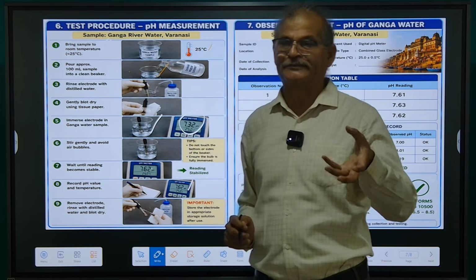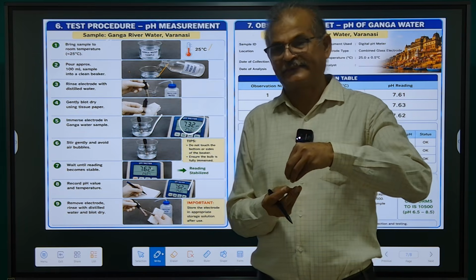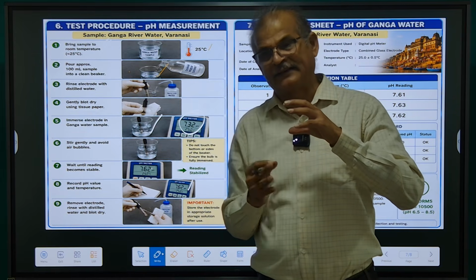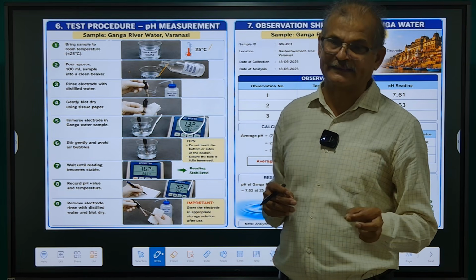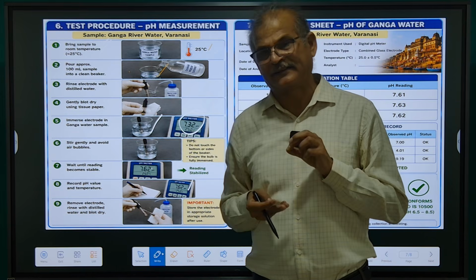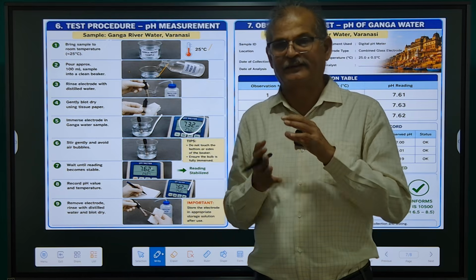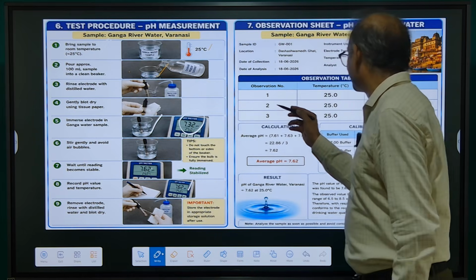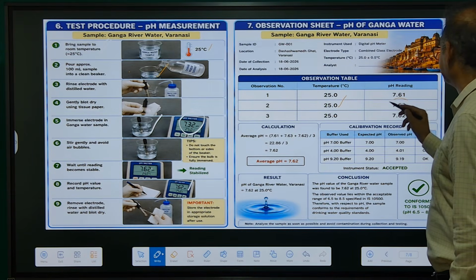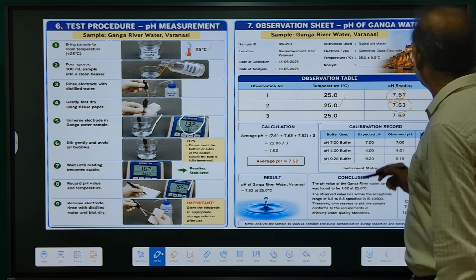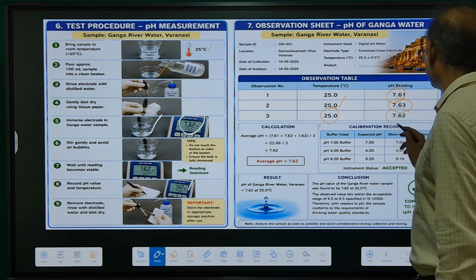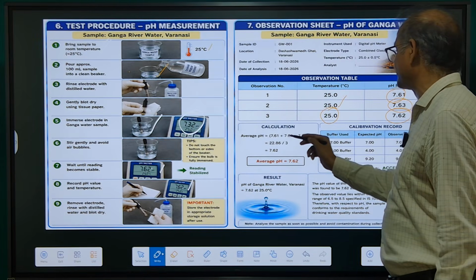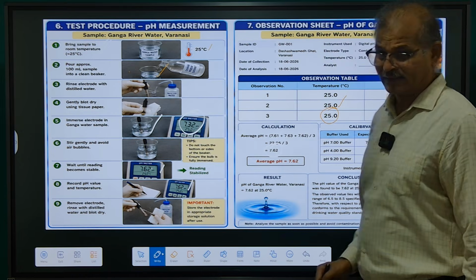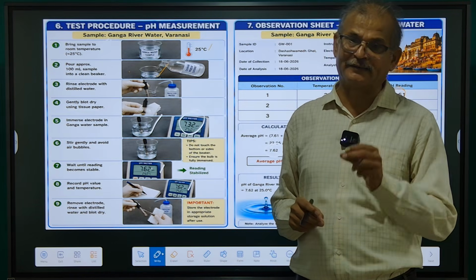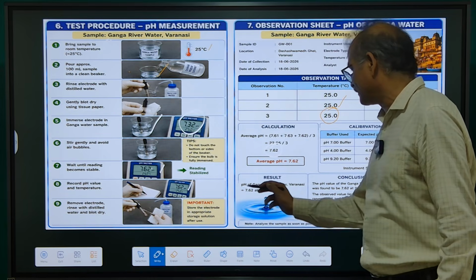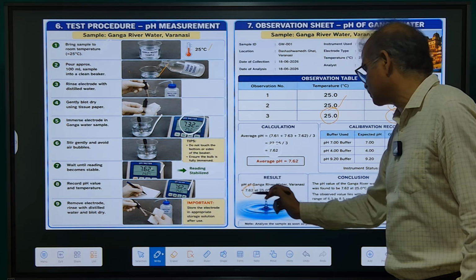Then when we have collected a number of solutions, say 5 or 6, we should repeat the same by rinsing the electrode again in distilled water, drying it with tissue paper, again placing it in the collected sample, stirring it gently, waiting for the reading to become stable, recording it, and likewise continuing. For the second, temperature recorded is 25 degree centigrade, pH reading is 7.63, whereas for the first solution it was 7.61. For the third solution at 25 degree it was 7.62. Then the average of 3, 7.61, 7.63, 7.62 divided by 3, will be 7.62. At what temperature the solution was recorded is very important. So it has been recorded as 25 degrees centigrade. It should also be mentioned. pH of Ganga River water recorded is 7.62 at 25 degrees centigrade.